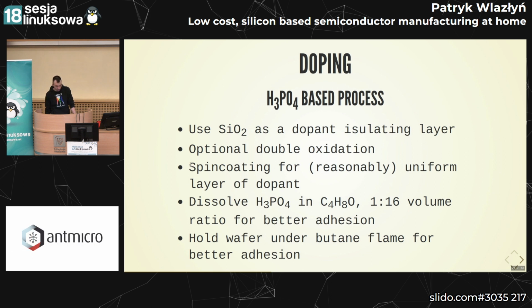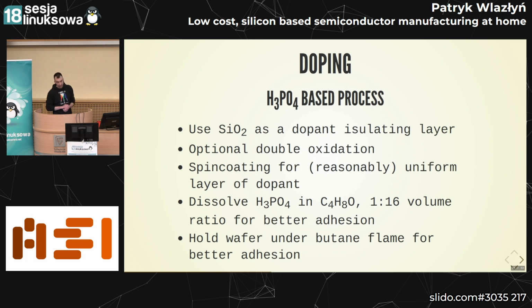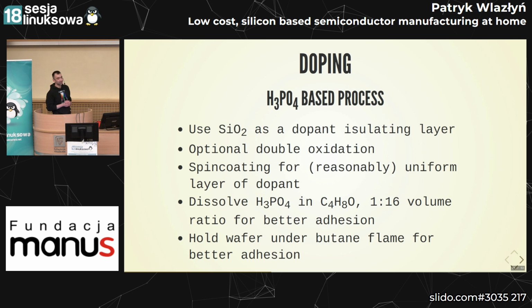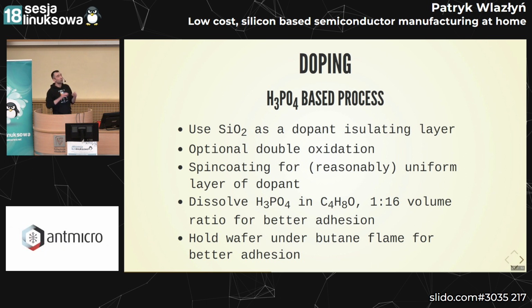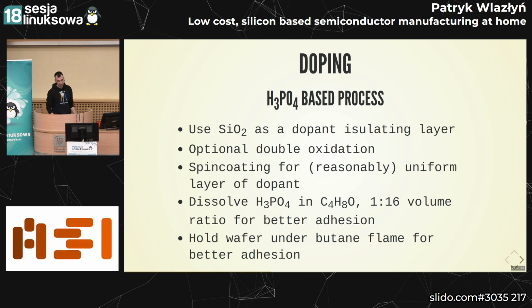Then we use spin coating. The phosphoric acid is a liquid, but we want to create a uniform layer on top of the wafer, and we use spin coating for it. It basically is placing a wafer on something that spins really fast, and it turns out it will create a very reasonable layer of the phosphoric acid on top of the wafer. For spin coating, we used a 12 volt computer fan, hacked around, and it works great and is very cheap.